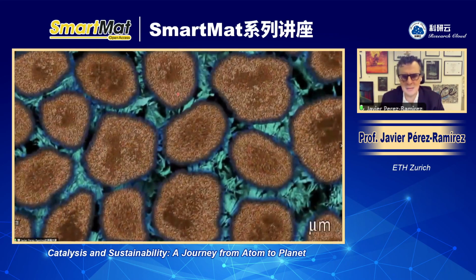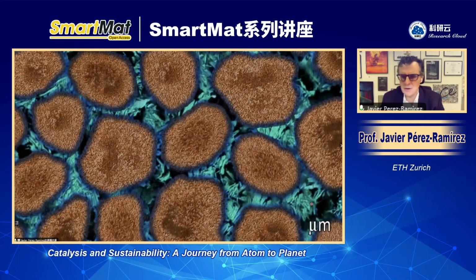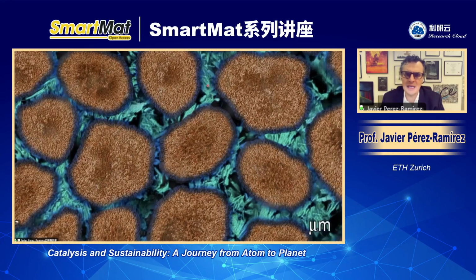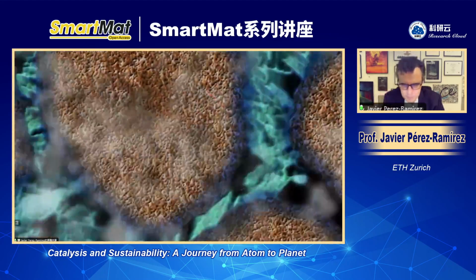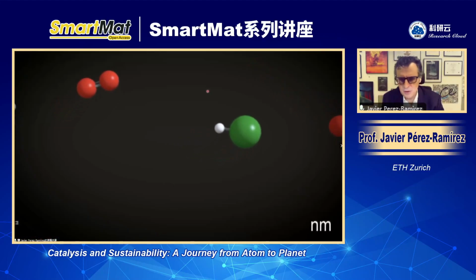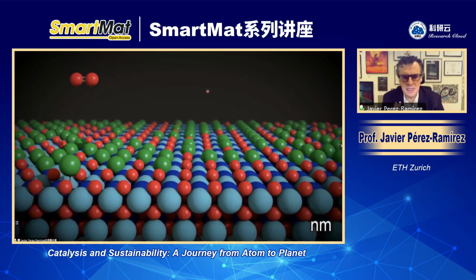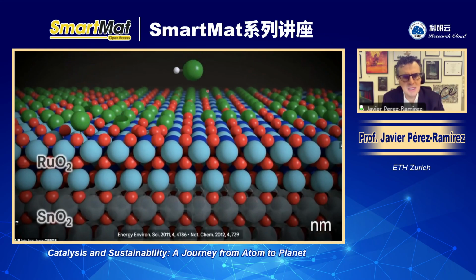And if we penetrate in the catalytic material, you are in the micron range, where you see in orange the support, in blue you have the active phase, and in green you have the binder to make particles. And if you go to the atomic scale, you see the catalytic surface that splits oxygen, cleaves HCl bond, OH groups recombine to produce water, and chlorine groups produce chlorine, recovering effectively chlorine.